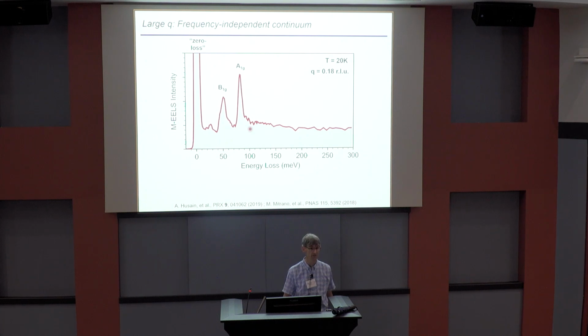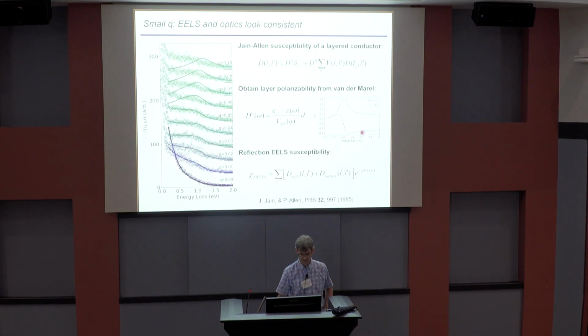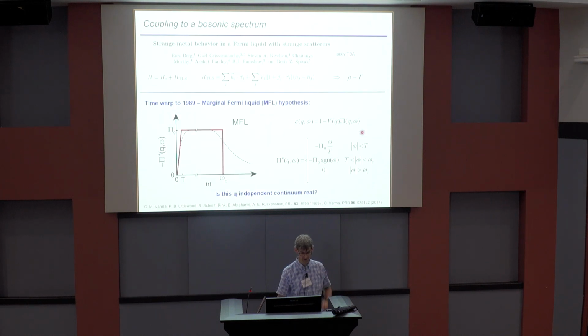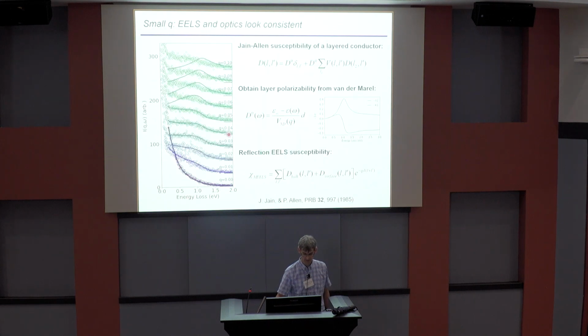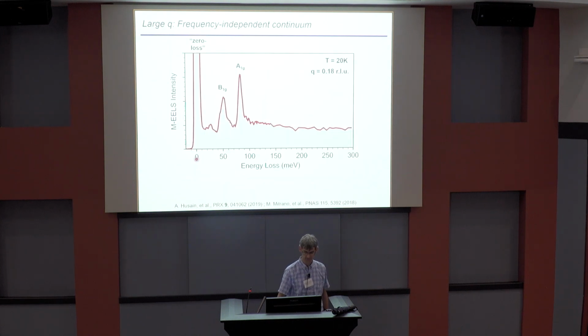There are some phonons. The phonons, by the way, line up exactly where you see the kinks in photoemission. Okay? And then underneath, there's a continuum. The continuum is flat, very flat. It's flat enough that it really looks quite a lot like this. So how flat is flat? Meaning from 0 to 300 meV, it looks almost constant.